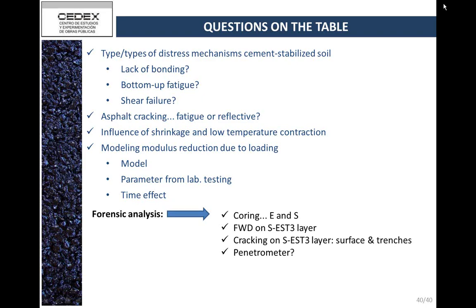Thank you. Can I just interject very quickly? Also, the horizontal slippage is actually such that you can see the slip on the surface, and you can see how the material in the wheel path and outside of the wheel path are moving longitudinally. So this slip is real, and you can see what is known in the English language as slickenside, a very slippery surface where it breaks the bond. But how can you see the slippage on the surface? Yes, see the slippage of the whole asphalt layer on top of the cement-treated layer.